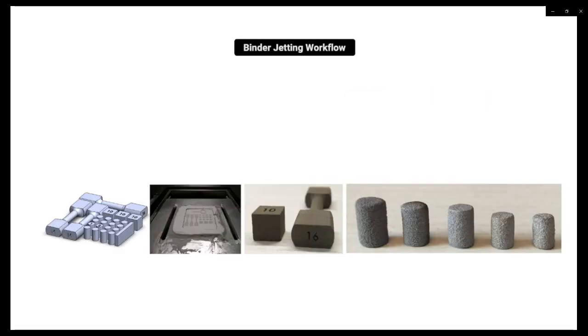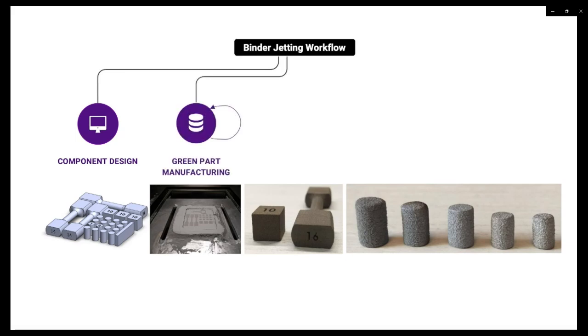Now that we know the principle behind binder jetting, let's take a closer look at the binder jetting additive manufacturing workflow. The first step is component design, which is done in computer-aided design environments. Once the designs are completed, they are transferred to the binder jetting machine for so-called green part manufacturing. Here, the part orientation and custom process parameters are programmed, and the parts are produced in a layer-by-layer fashion. It is often necessary to iterate and optimize process parameters to improve geometric fidelity and green part density. Parts in this state are between 50 to 65% dense. Once the green parts are manufactured, the binder or glue is cured by exposure to heat, either inside the machine or in a curing oven, and the parts are depowdered and cleaned.